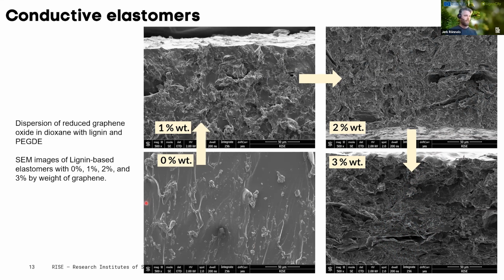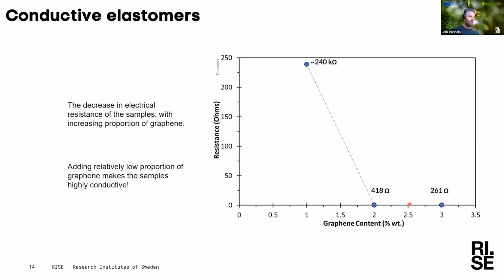And you can see here our SEM images of having no graphene at all, 1 weight percent graphene, 2 weight percent, and 3 weight percent. Although it looks messy, it's homogeneous, which means that the graphene is well dispersed in there, which is a first interesting result. And then, to make a long story very short, we investigated the conductivity of these, or rather the resistance of these. So here on the y-axis, we have the resistance in kilo ohms. It says thousands very faintly up there. And here we have the graphene content in weight percent. So we made 3 samples with 1, 2, and 3% graphene in it.